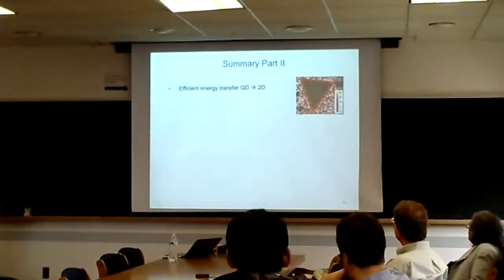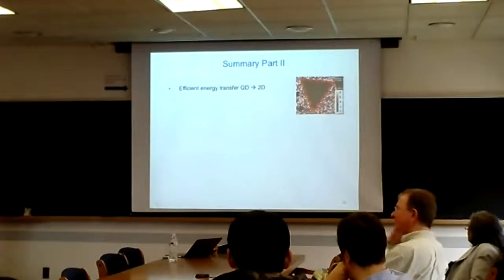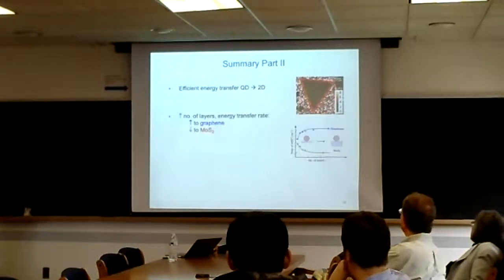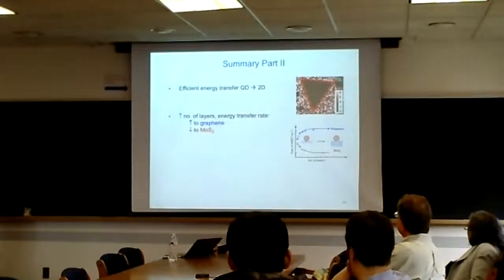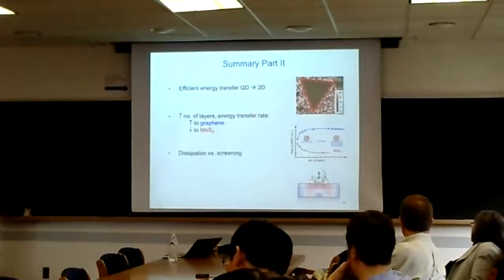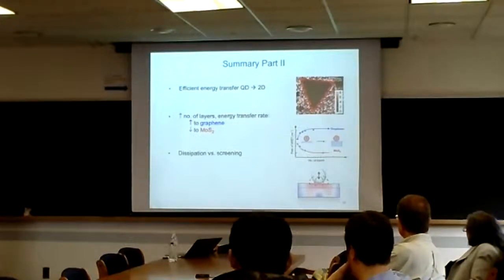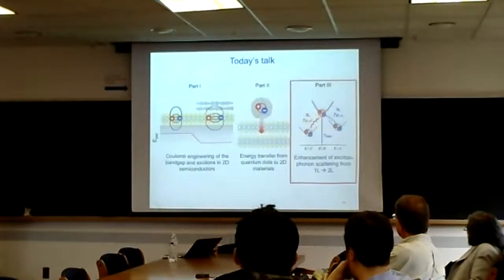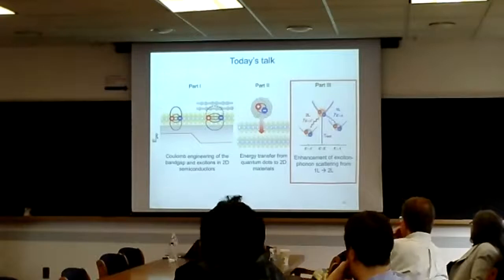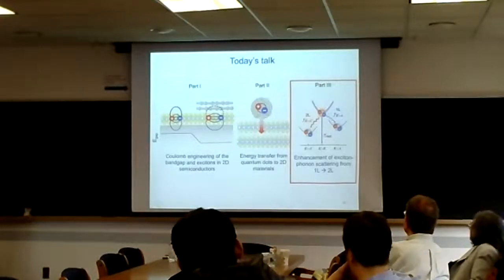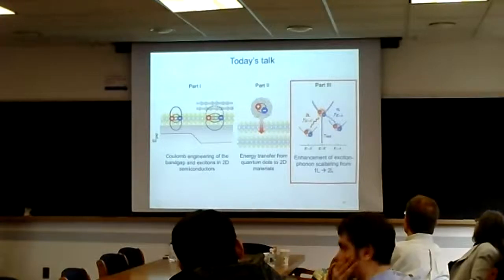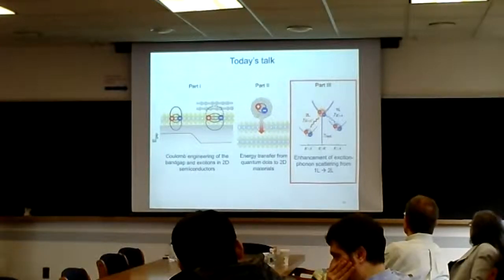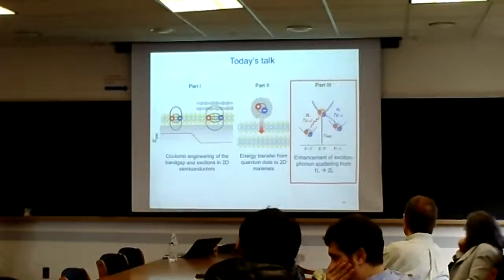So you can have a really efficient energy transfer from quantum dots to 2D materials. The thickness-dependent trends can sometimes be unusual, and we were able to explain this as a competition between the dissipation and the screening in these systems, and we made some predictions for other systems as well. So in the final part, in my remaining few minutes, this is fairly short, I just want to tell you a little bit about how the local dielectric environment, or adding layers, increasing from monolayer to few layers, affects exciton-phonon interactions in these systems.